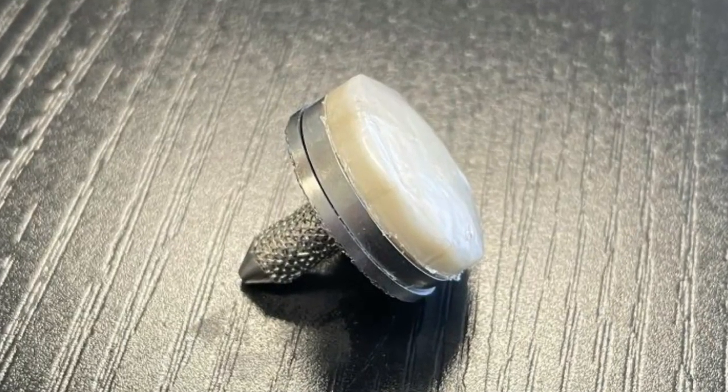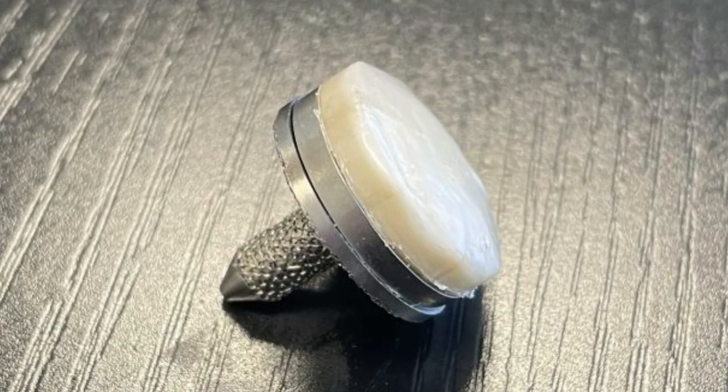One challenge was achieving the upper limits of cartilage's strength. Activities like hopping, lunging, or climbing stairs put some 10 MPa of pressure on the cartilage in the knee, or about 1,400 pounds per square inch — but the tissue can take up to four times that before it breaks. In the past, researchers used a freeze-thaw process to produce crystals within the gel to hold the polymer chains together. In the new study, instead of freezing and thawing the hydrogel, the researchers used a heat treatment called annealing to cause even more crystals to form within the polymer network. By increasing the crystal content, they produced a gel that can withstand five times as much stress from pulling and nearly twice as much squeezing compared to freeze-thaw methods.